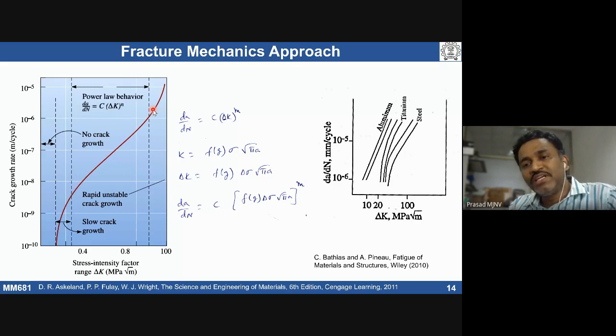One, if the material has failed, it will have a fracture surface, and with a naked eye, if it has beach marks, that's one indication at a macro level. If we go to a little bit micro level, if I do fractography, I see striations. And if I look just at the surface itself with a little bit of low magnification, we see formation of intrusions and extrusions. That's also an indication that the material has undergone cyclic loading conditions.